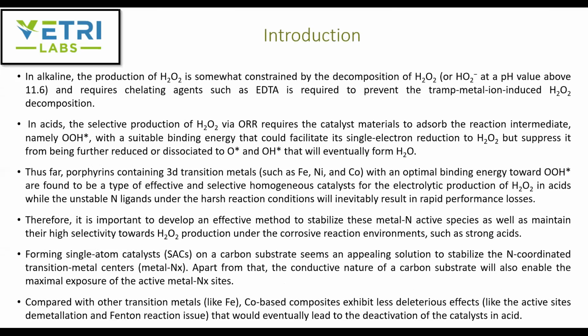In alkaline media, the production of peroxide is somewhat constrained because of the decomposition of peroxide at a pH value above 11.6, and it requires chelating agents such as EDTA to prevent this decomposition. So it works best in acidic media, because the selective production of peroxide via the oxygen reduction reaction requires the catalyst materials to adsorb the reaction intermediate with a suitable binding energy that could facilitate its single electron reduction to peroxide,